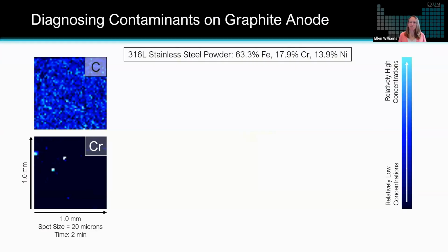So the first application example that we'll look at was a graphite anode sample that had known contaminants that were stainless steel powders. So we analyzed this anode with a 1 millimeter by 1 millimeter elemental map with a 20 micron spot size that we did very quickly. It took about 2 minutes. And you can see how there is relatively high amounts of carbon shown in blue and bright blue. That's what we would expect on a graphite anode, which is mostly carbon.